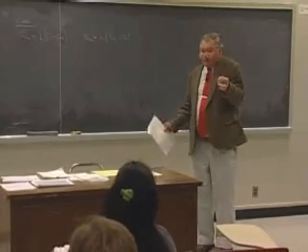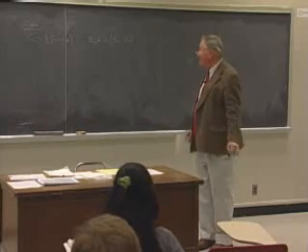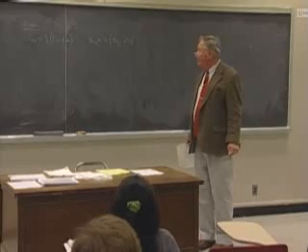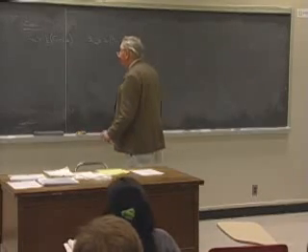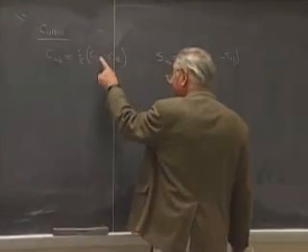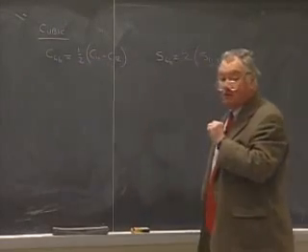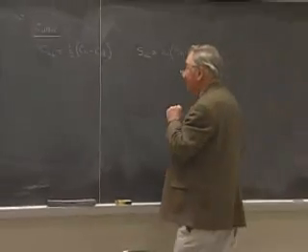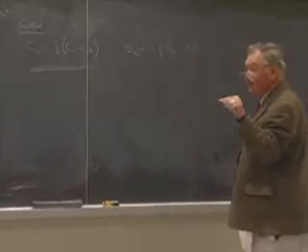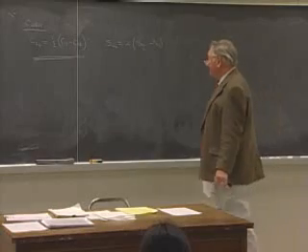Well, they have to be, in terms of the tensor, the same sort of equality. And the reason they don't look the same is because of our different absorption of the factors of 2 and 4 in defining the stiffnesses and in defining the compliances. Remember that for the CIJKLs, there was no factor of 2 or 4 introduced in defining the matrix elements. So this one is okay. This is a true equality between tensor elements for any tensor whatsoever of 4th rank for a cubic crystal.